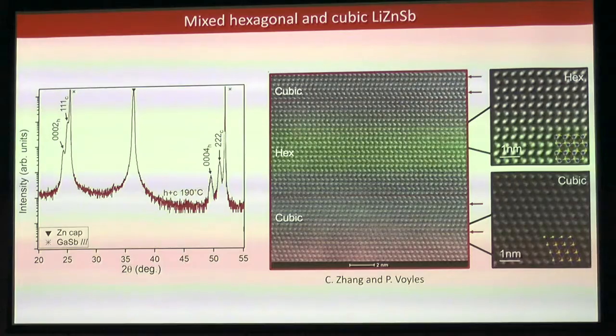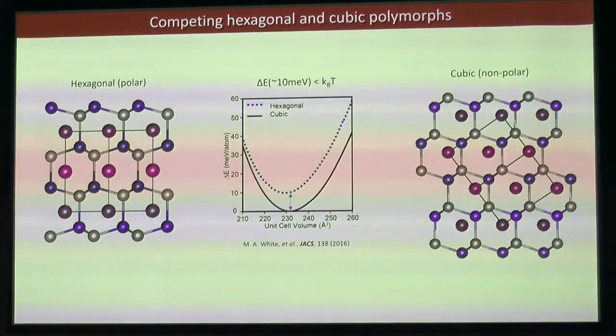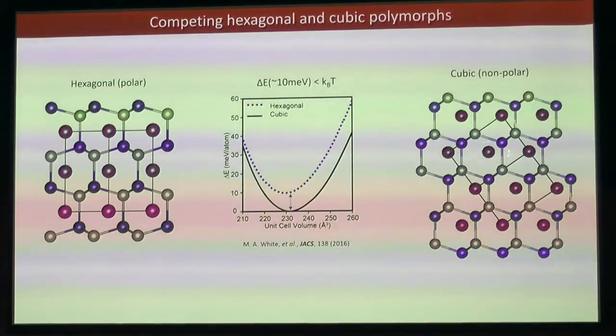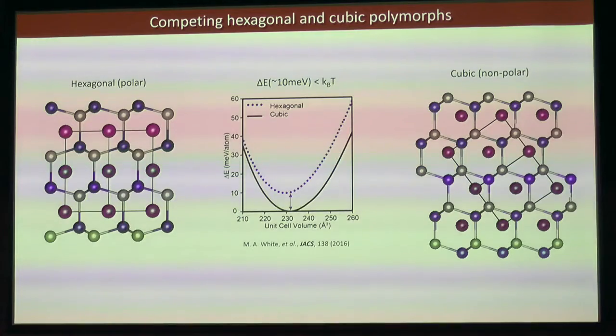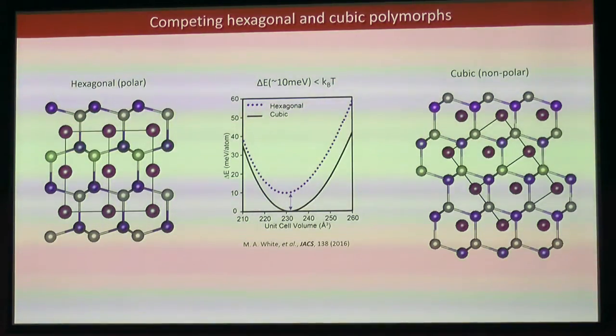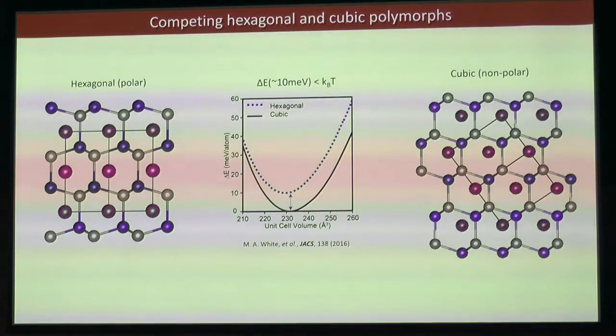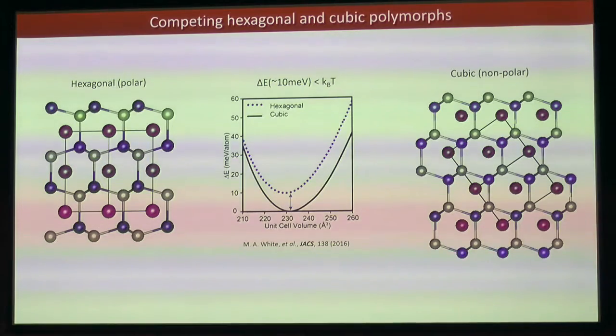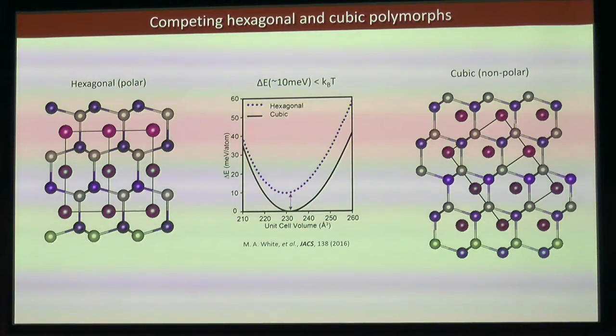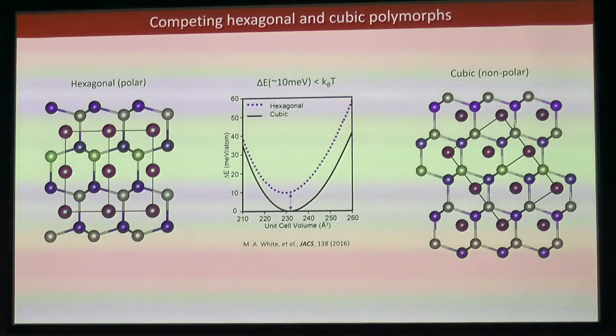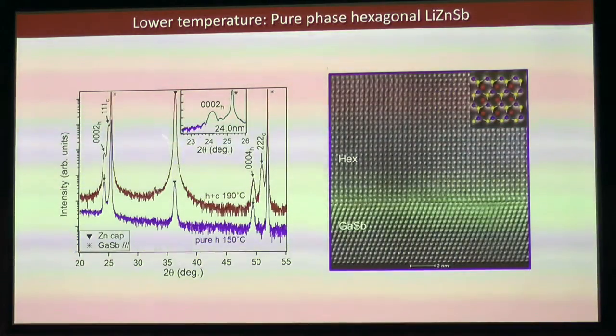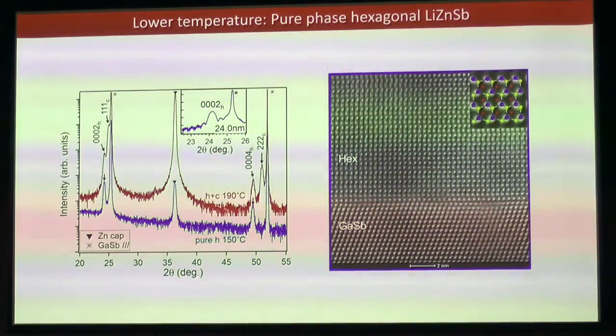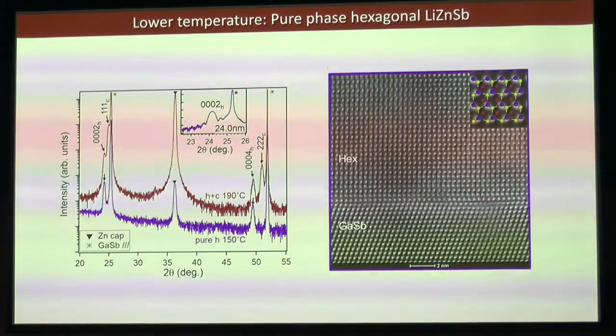Okay? If we look a little more carefully, cubic is a competing polymorph with the desired hexagonal phase. This nonpolar cubic phase is actually, at the level of DFT, the lower energy phase, but not by much, about 10 meV per atom. That's pretty small compared to kT, especially at elevated growth temperatures. So it's reasonable to expect that at moderately high growth temperatures, we're going to have a mix of both phases. So instead of this moderate temperature growth at 190, we cool the growth down and grow at 150.